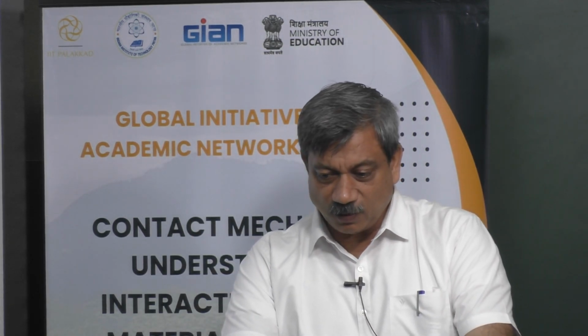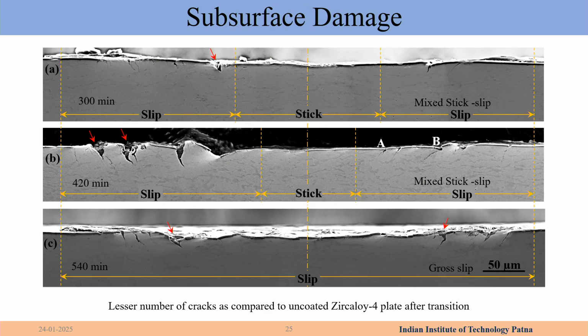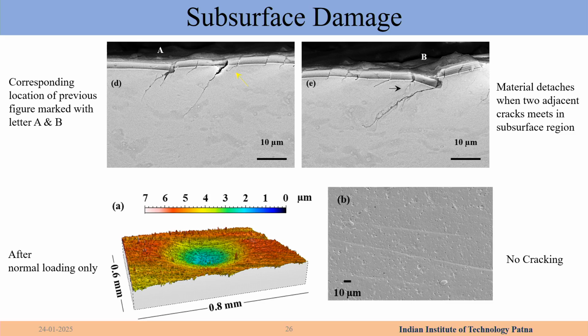So you can see the subsurface damage with titanium nitride. This is much clearer here. This is that coating here. You can see the cracks being formed, and this is how it has collapsed. The cracks are much less actually, if you know the plots we saw without titanium nitride. But then titanium nitride itself also creates these pieces which can come off.